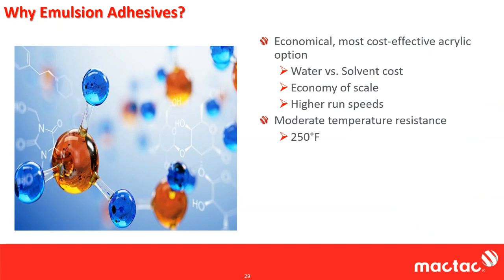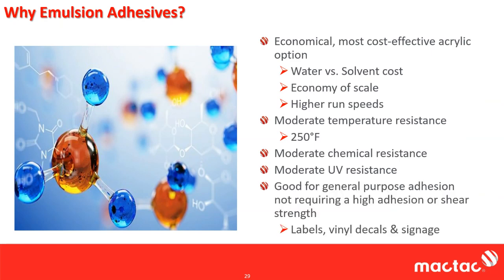Emulsion acrylics, especially compared to rubber, and I'm going to have a table up here where I compare all these attributes to each other with a rubber, you still get pretty moderate temperature resistance out of an emulsion acrylic, around 250. A lot of rubbers crap out about 180, you get about 250 out of an emulsion. You do get some moderate chemical resistance, especially on the plasticizer side. You're going to get the UV resistance. Again, better than a rubber, not quite as good as a solvent acrylic, but still pretty good.